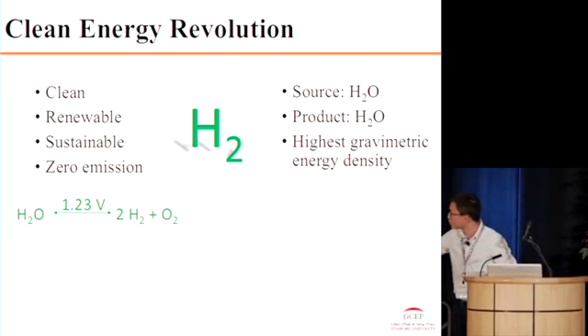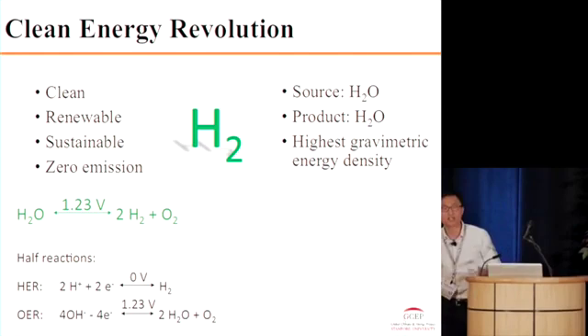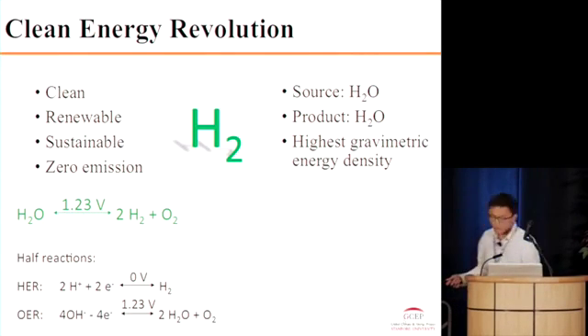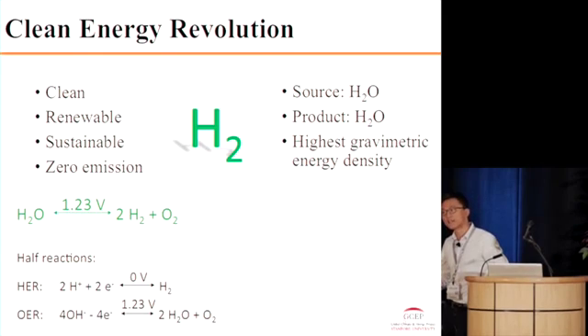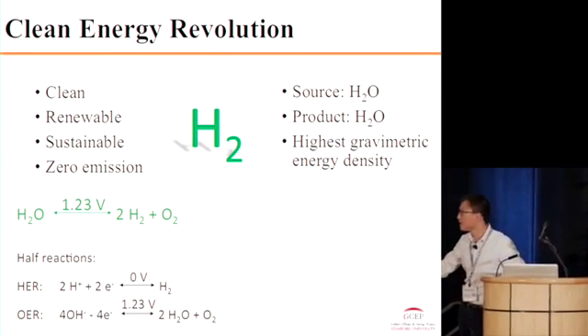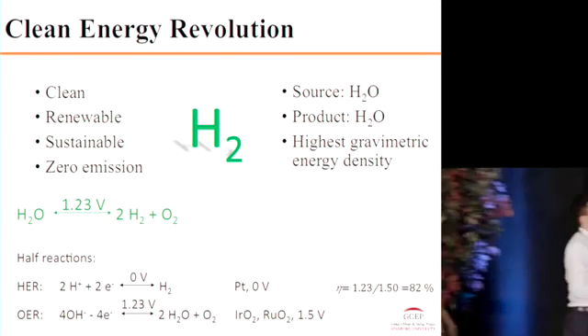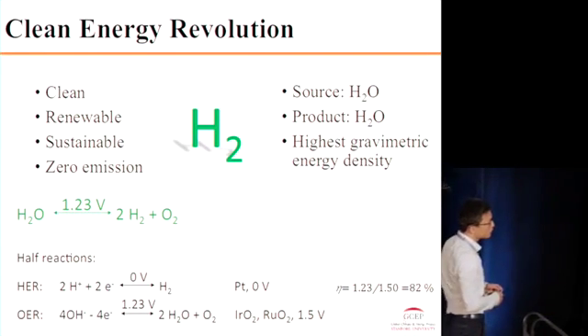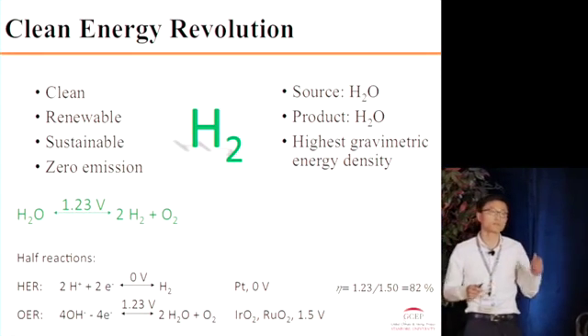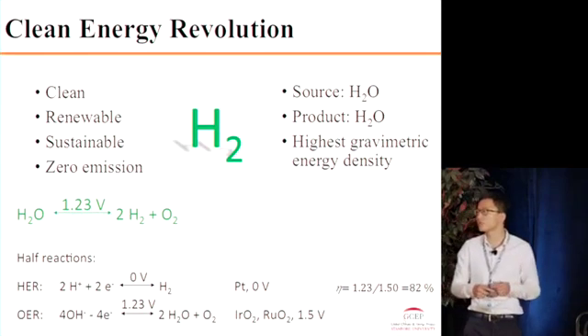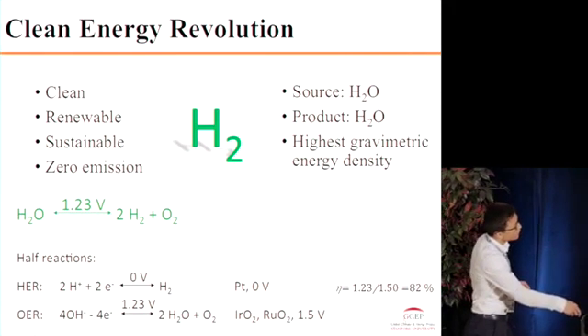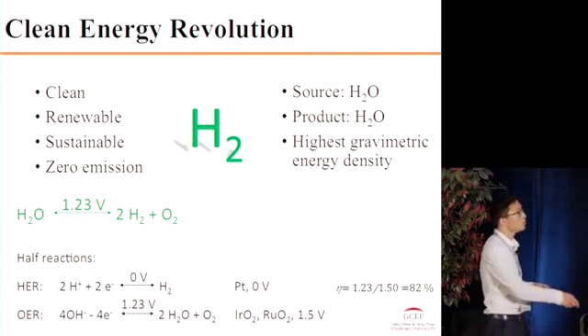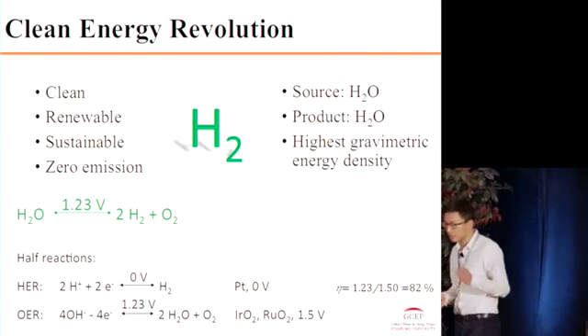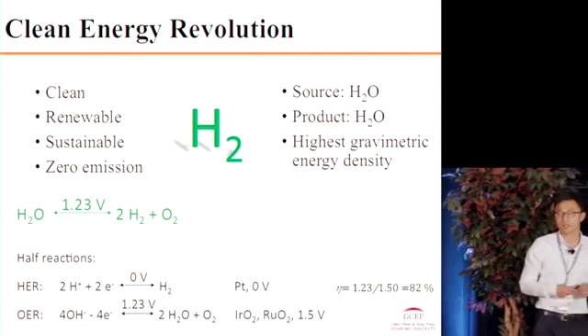If we look deeper into the full reaction of water splitting by electrocatalysis, there are actually two half reactions. One is the hydrogen evolution reaction, where you reduce the proton into hydrogen. The other is the oxygen evolution reaction, where you oxidize water into oxygen. We have very good catalysts made of noble metals, such as platinum, which can drive the hydrogen evolution at even zero overpotential. For the oxygen evolution reaction, we have iridium oxide and ruthenium oxide, which are very efficient catalysts, but still require several hundred millivolts of overpotential to drive the oxygen evolution. If you add the two starting points together, it can easily give you an efficiency of electricity conversion to hydrogen energy of more than 80%, which is really high.